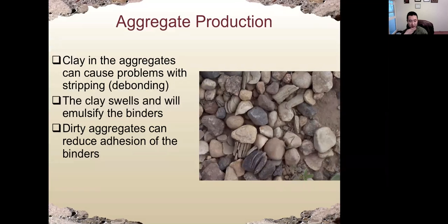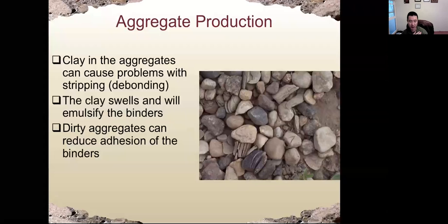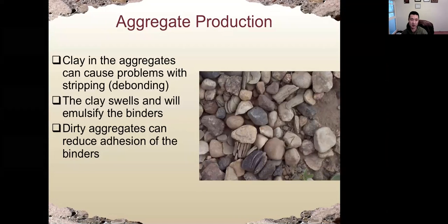Here we talk about more details on aggregate production. The clay on the surface of aggregate can cause problems such as stripping or debonding. Another potential problem is clay may make the asphalt cement swell and emulsify the binder. So emulsify means make the binder soft. Okay, which is not good. And dirty aggregate can also reduce adhesion of the binder. So we need to clean the aggregate before mixing with the asphalt binder.